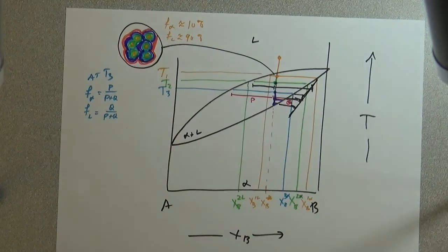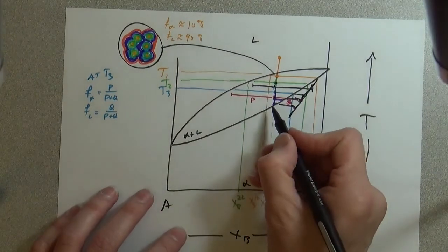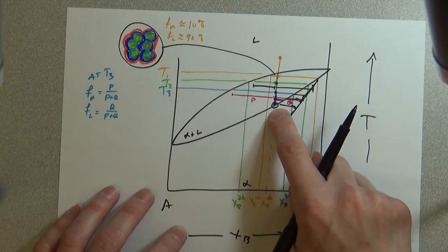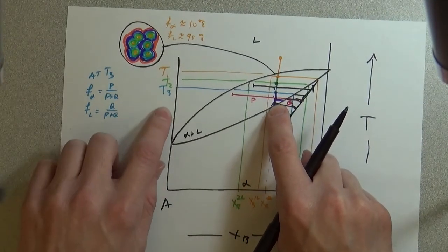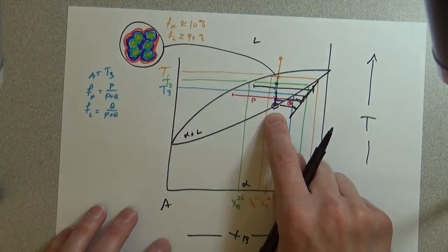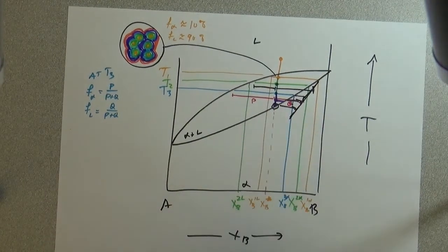And what this means is that when we reach where the original equilibrium boundary is, and cross the temperature below that, which should result in the removal of the liquid, well, we still have liquid.